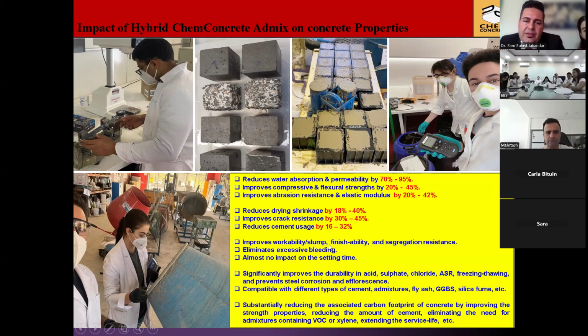Improves workability, finishability, segregation resistance, eliminates excessive bleeding, almost has no impact on setting time or heat of hydration, significantly improves the durability in acid, sulfate, chloride, ASR, freezing thawing, and also prevents steel corrosion and efflorescence. It substantially reduces the associated carbon footprint by improving the strength properties, reducing the amount of cement, eliminating the need for admixtures containing VOC or xylene, and also extending the service life of concrete.